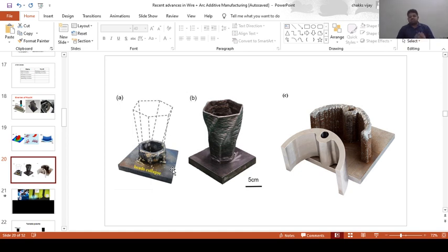Prior to that, we generally do 3D slicing, in the sense that the exact geometry is sliced into small segments. After that slicing, we do a modeling process, then come up with a simulation, and if that works, we go for pilot experiments. During these pilot experiments, we may end up with spatters and even irregular deposition, so each time we optimize all the process parameters.